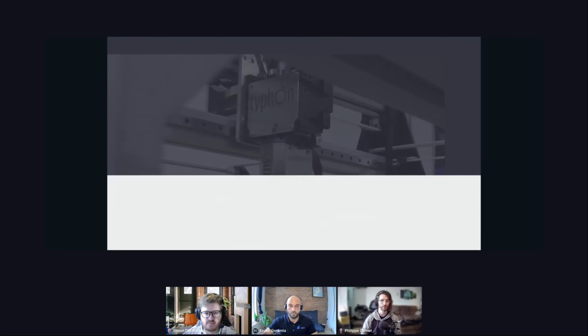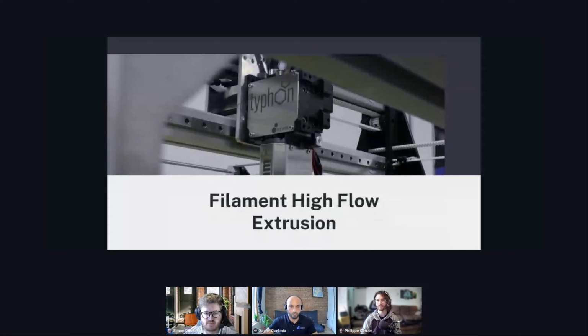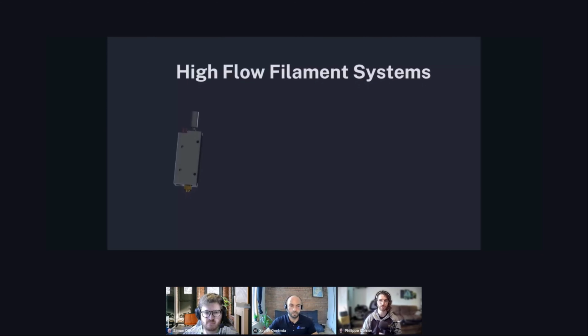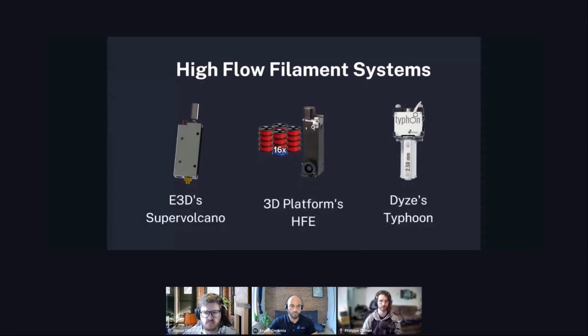I'll start with the filament-based high-flow extrusion and then follow with the pellets-based high-flow extrusions. One way to increase profitability is using a high-flow or high-output filament extruder. The extruder throughput is the limiting factor for printing speed, where a printer can easily move the carriage faster than the extrusion system can deposit the material. Using a high-flow extruder removes this bottleneck, each printer being able to make a 3D printed part faster.